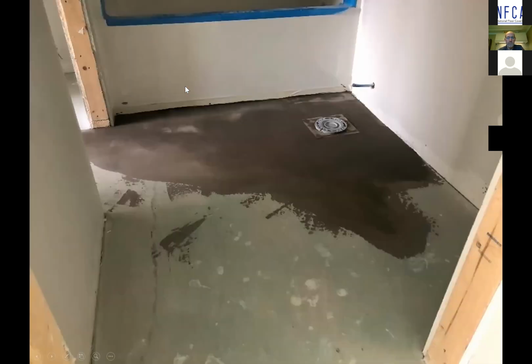Okay, so moving along, that's not uncommon. We've got to do some type of prep, but also this is not to say that all gypsum is bad. So here's an example of a floor where the gypsum was in pretty good shape. And what we're using here is a primer. So you can see it's a little bit hazy there, kind of that light green kind of effect. And the guys had to do some patching and some preparation. They were a little low around the toilet connection here, and also just to smooth it over. So they had to patch.